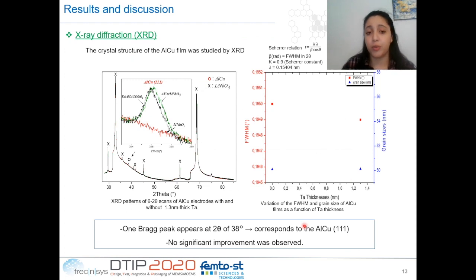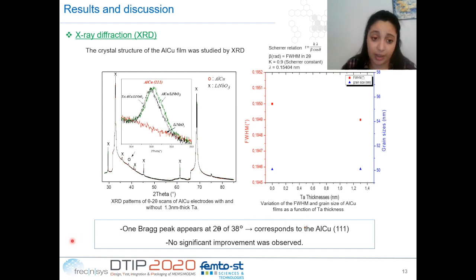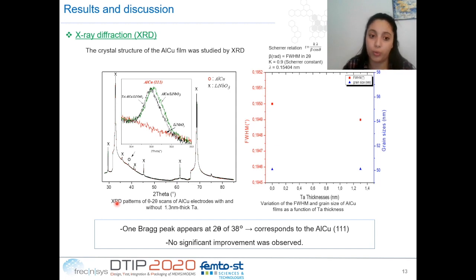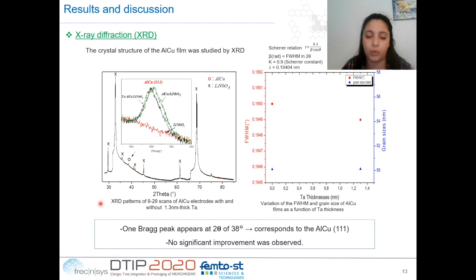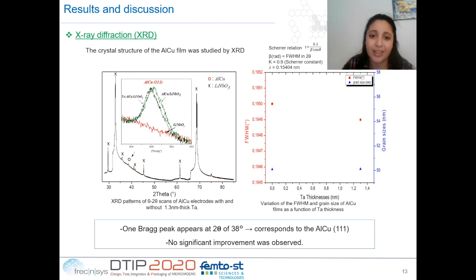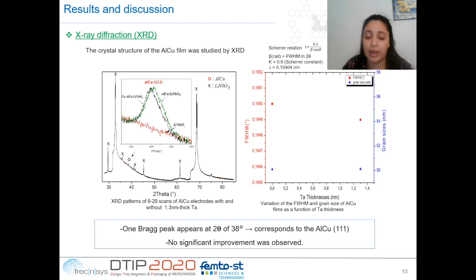The crystal structure of aluminium-copper films deposited directly on lithium niobate and with 1.3 nm of tantalum underlayer was studied by XRD. We can clearly see that only one Bragg peak appears at 38°, corresponding to the aluminium-copper 111 plane. The presence of only the AlCu 111 peak without other peaks demonstrates that 111-textured aluminium-copper is developed on the lithium niobate substrate. In the presence of 1.3 nm of tantalum underlayer, this peak becomes slightly narrower, but in this experiment we were not yet able to conclusively determine whether 1.3 nm of tantalum truly improves the crystalline quality.